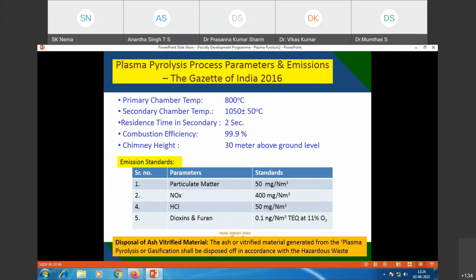Here the CPCB, in the Gazette of India, has mentioned that primary chamber temperature should be 800, secondary chamber temperature should be 1050 plus or minus 50 degrees centigrade. Residence time in the secondary should be 2 seconds, and the combustion efficiency should be 99.9%. The chimney height should be 30 meters from the ground level.